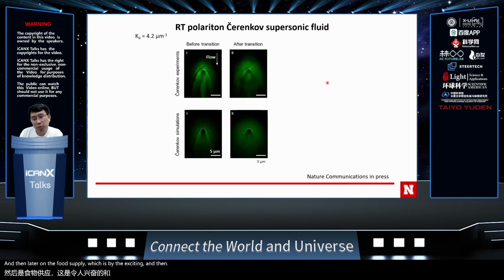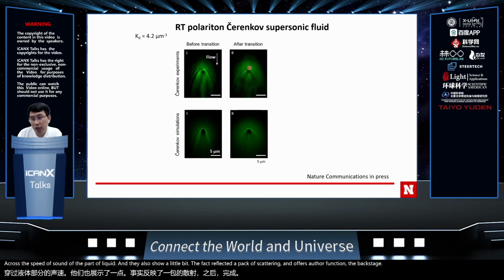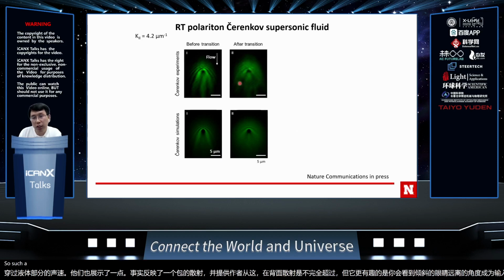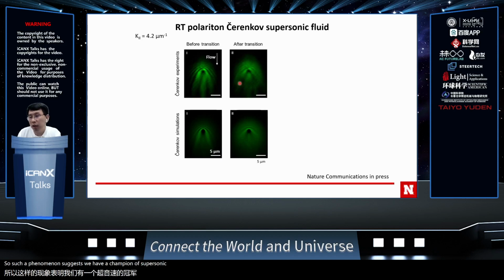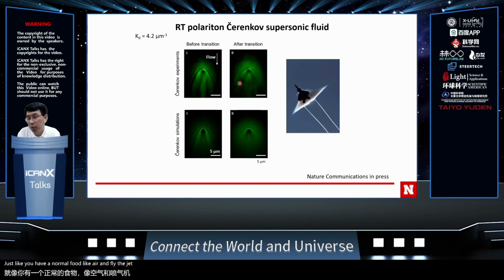Another experiment we did is to continue increasing the pump angle, so that we have higher in-plane momentum. As you can see, at lower pump power they show a linearized wavefront, because the flow speed is well beyond the speed of sound of the polariton liquid, and they also show a little back scattering. After the transition, the backscattering is not fully suppressed, but what's more interesting is that the linearized wavefront angle increases. Such a phenomenon suggests we have a Cherenkov supersonic fluid, just like when you fly a jet beyond the speed of sound in air and see the Mach cone. This means the superfluidity state has been broken simply by flowing at higher speed, which makes our system pretty ideal.